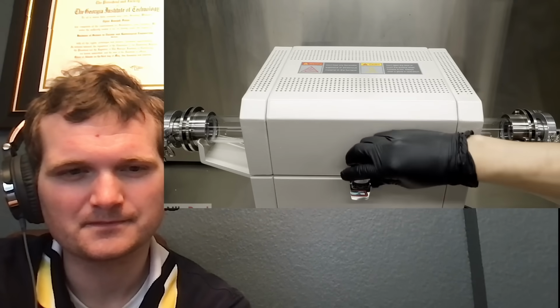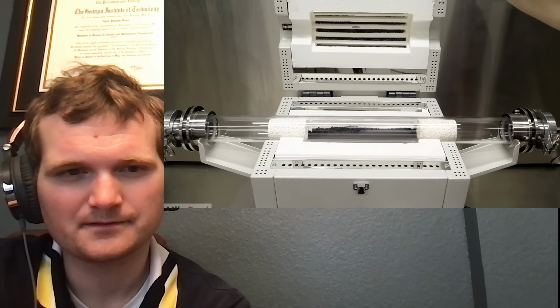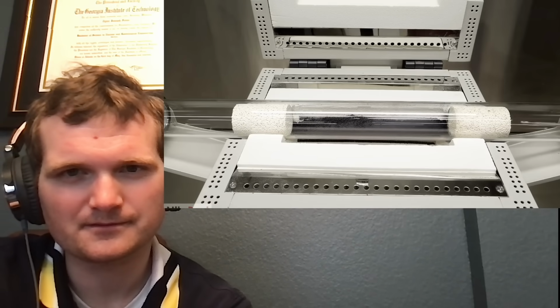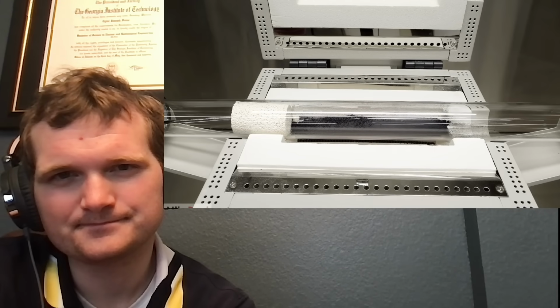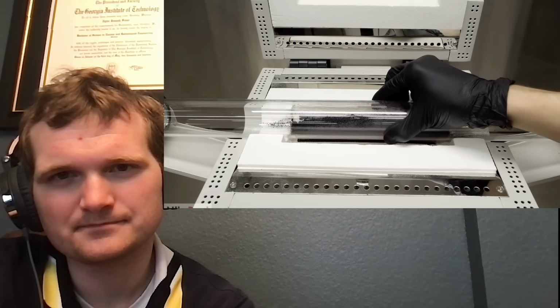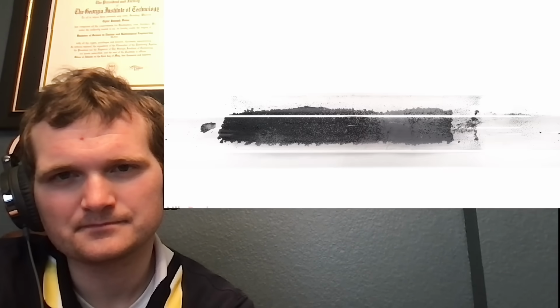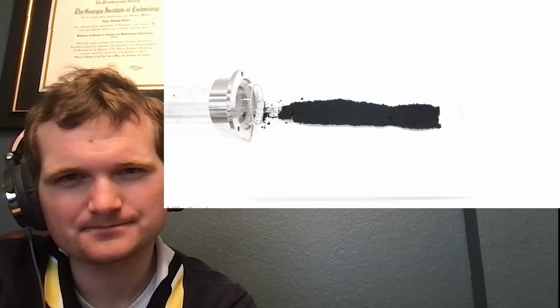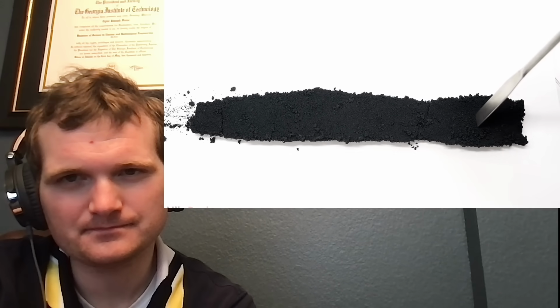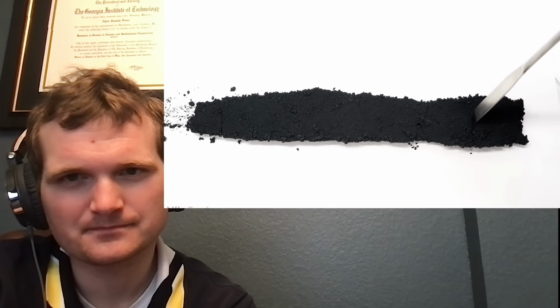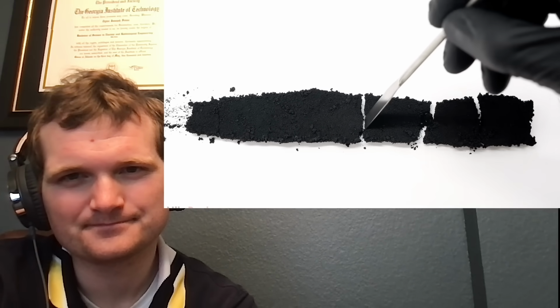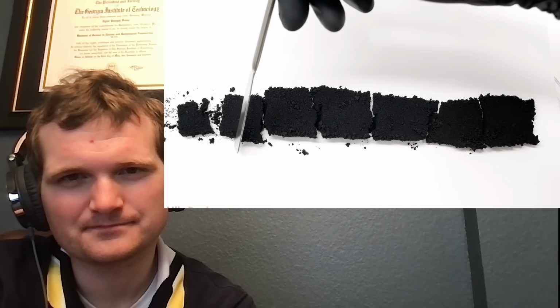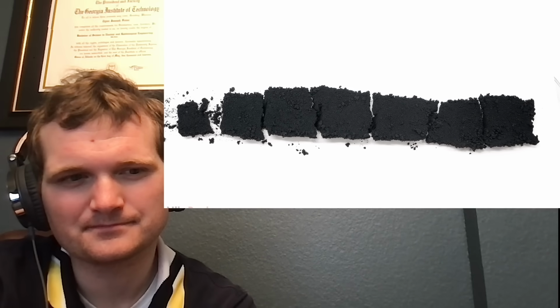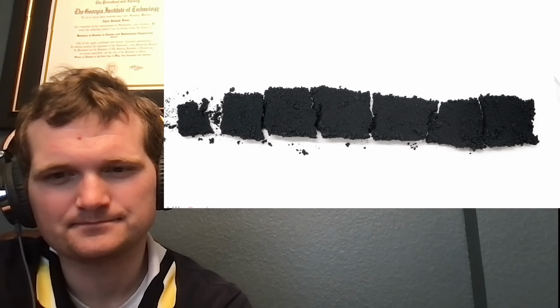The next day, I opened the furnace, and the first thing that I noticed was that the powder was a lot blacker, and that it had also shrunk. I then took off most of the metal attachments on the sides, and I pulled out the white blocks. To get it out of the tube, I carefully pushed it with a glass rod. Delicate operation. What I had now was definitely more dense than before, but it was still pretty fluffy and fragile. In theory, though, this should have been YBCO, and I wanted to see if it was able to superconduct.